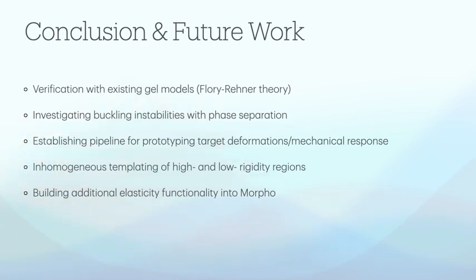To conclude, we have simulated the equilibrium state of a gel under various inhomogeneous conditions by using a model that incorporates elastic and concentration energy costs. Our code, implemented in the open source Morpho software, aims to minimize those energetic costs while maximizing shape elasticity over different deformed domains. These produce concentration profiles that align with what we would expect.